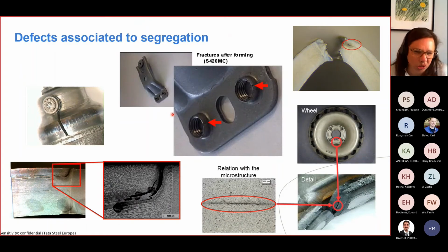But why do we do all this? Why are we going through the whole thermodynamic evaluation, the whole phase field approach, and all those painful measurements and tests and everything? It's simply because segregation is that fingerprint from the solidification that will mark many, many final product properties. Moreover, many defects on the product will be directly associated to segregation. I have some horrible examples here. They look horrible, really. One example is here.